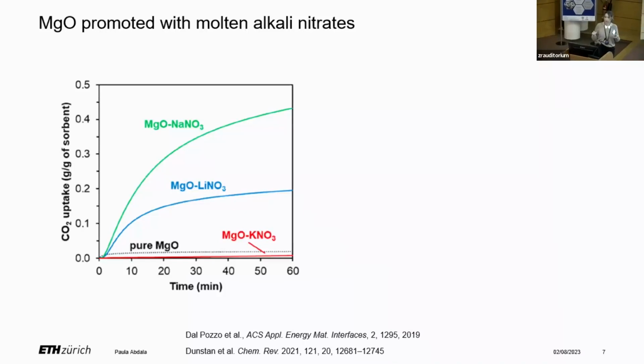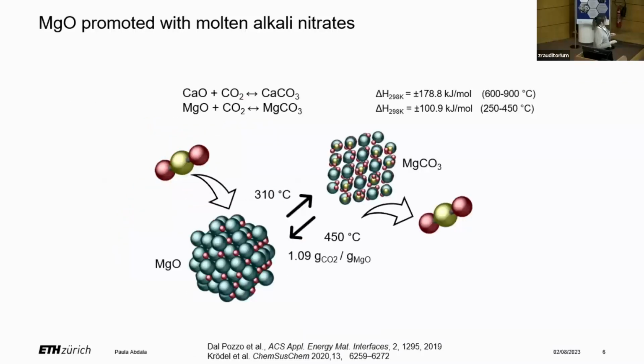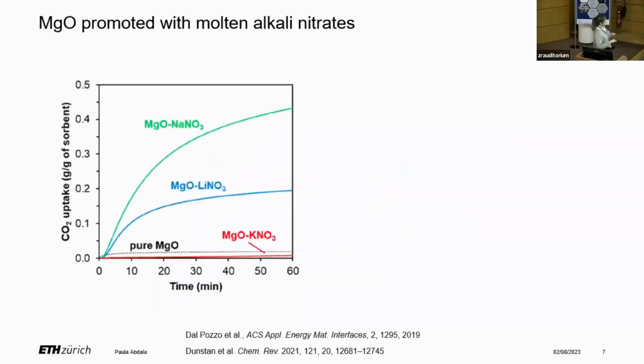However, in practice, if you expose magnesium oxide to a stream of CO2 under thermodynamically allowed conditions for its carbonation, the actual uptake is very low, this dashed line here. And a solution to this drawback has been the addition of promoters, typically salts that under CO2 capture condition are molten. For example, here you can see if we add sodium nitrate, which is molten, at 380 degrees, we can drastically enhance the carbonation of magnesium oxide. And how does this promoter work?